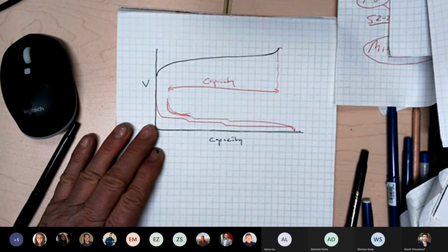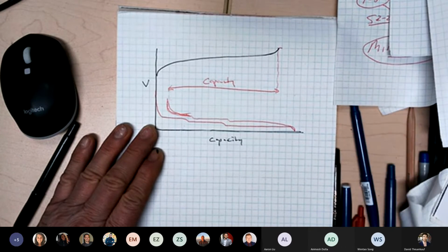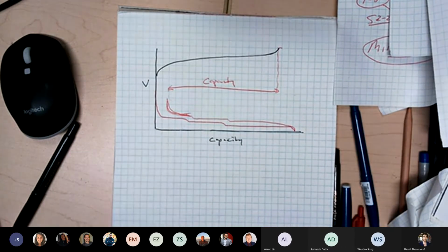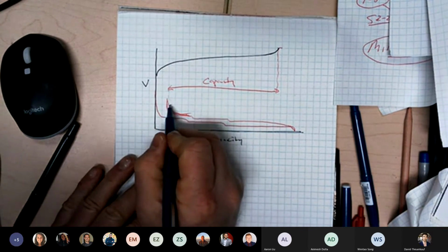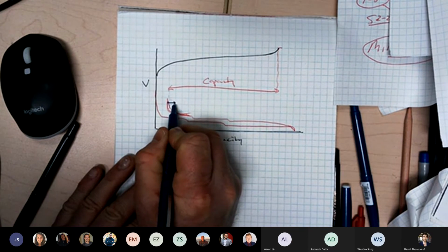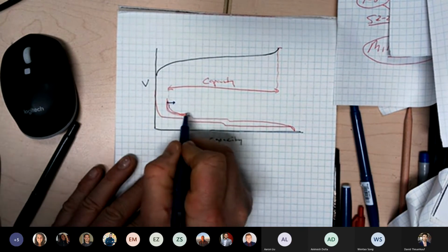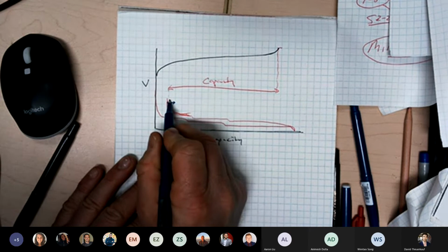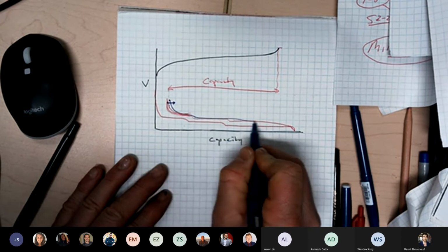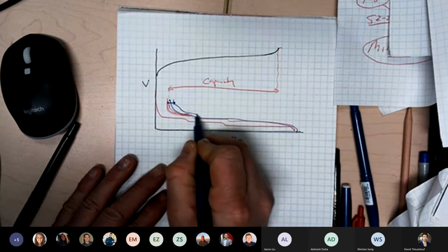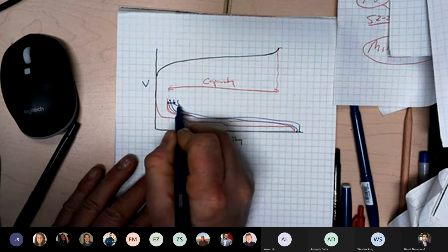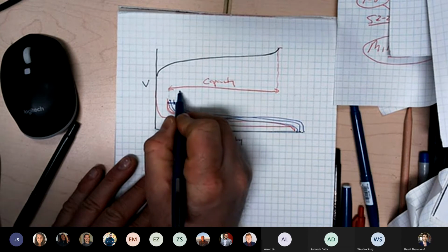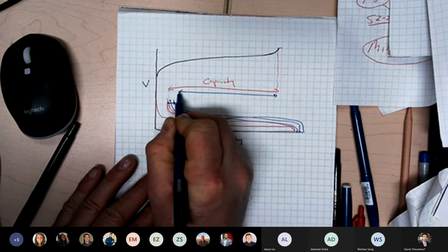But what we learned in our study of the lithium graphite cell was that slowly, every cycle, this curve just keeps shifting to the right. We saw it. We know it happens. So on the next cycle, it's here, and the next cycle, it's here, and the next cycle, it's over here. Keeps shifting to the right. And what that means is the cell capacity gets smaller and smaller.